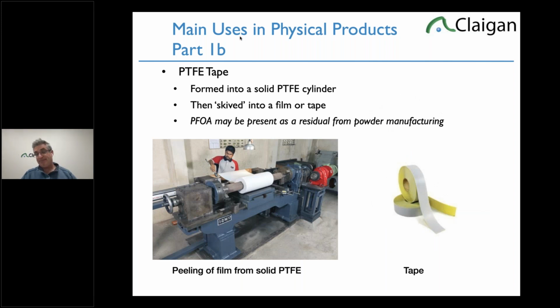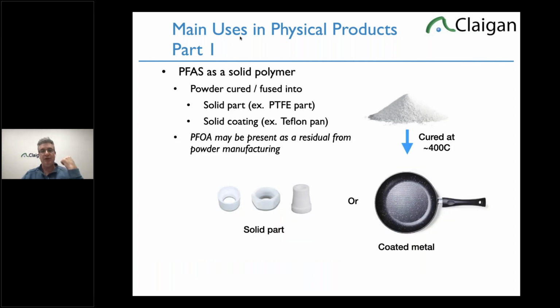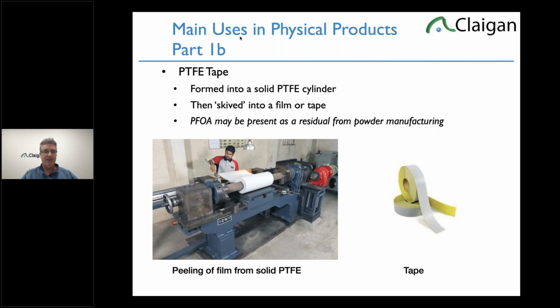Another solid one is pretty funny. It's actually PTFE tape. PTFE tape is actually a solid done in the same way. So what you do is you take the powder, you put it into a mold of a huge cylinder, you fuse it, just like the stuff on the left, you heat it up, you fuse it, and you create this hard cylinder. Then you skive it. And skiving is basically peeling. You put a blade on it, and you peel super thin layers off the solid piece. That's skiving. And then you take that super thin layer, you add adhesive to it, then release paper, and you roll it again into a second roll, and then you section it, and that's PTFE tape. So PTFE tape is intentionally added PTFE powder, which is fused together in a solid and then skived off, basically peeled. It can have PFOA residual because if the powder was manufactured with PFOA as a manufacturing aid, the tape will have it. But it doesn't have to. PTFE tape is actually just a super thin version of the solid, and they make a solid, they skive it off.